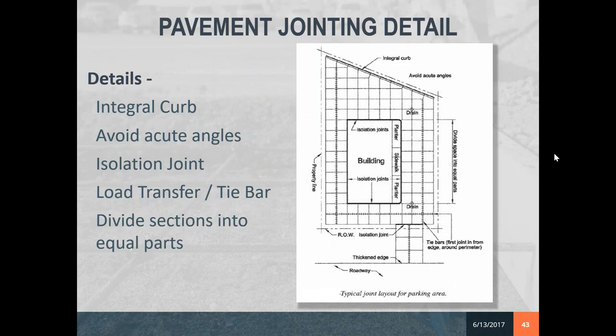ACI code also has a layout and recommended suggestions. Again, you want to make sure that when you're lining up your control joints and saw joints, they match up in the curb also. I've been to a lot of job sites where the pavement, such as in a parking lot, has an expansion joint, and then the curb is poured continuously over that joint. When the expansion joint starts to move, it's going to crack that curbing. So you want to make sure those line up. Again, your isolation joints, your control joints.